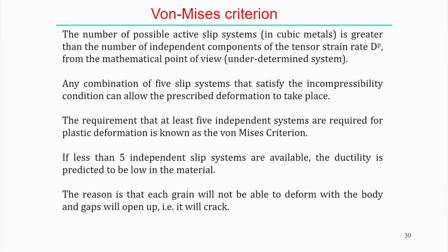The requirement that at least 5 independent slip systems are required for plastic deformation is known as the von Mises criteria. But if fewer than 5 independent slip systems are available, the ductility is predicted to be low in the material. The reason is that each grain will not be able to deform with the body and gaps will open up, that means it will crack. So basically the compatibility condition is the main issue.